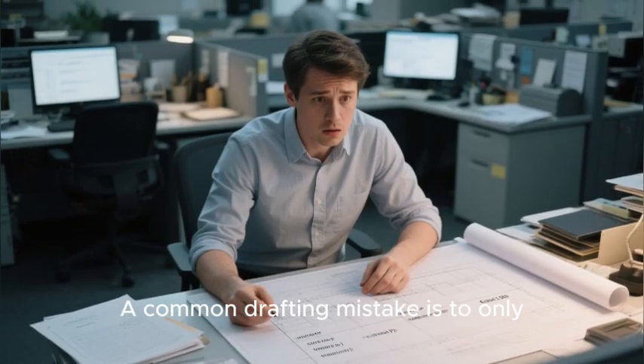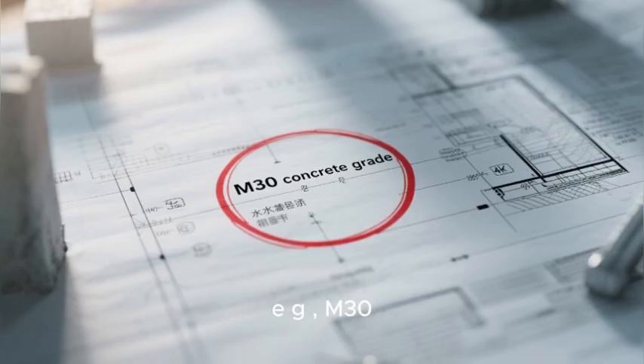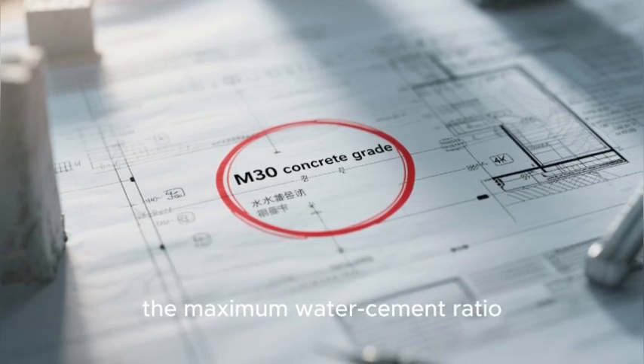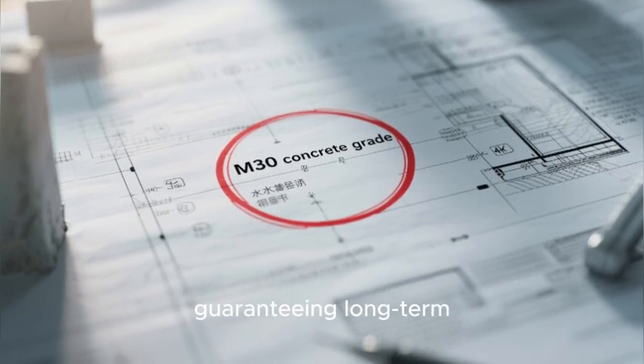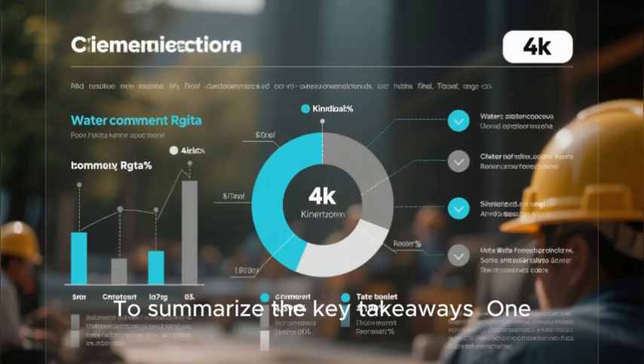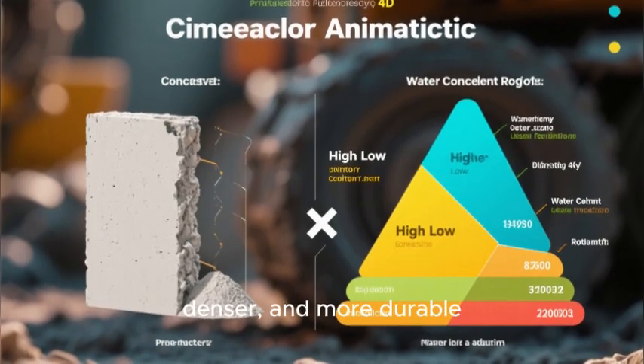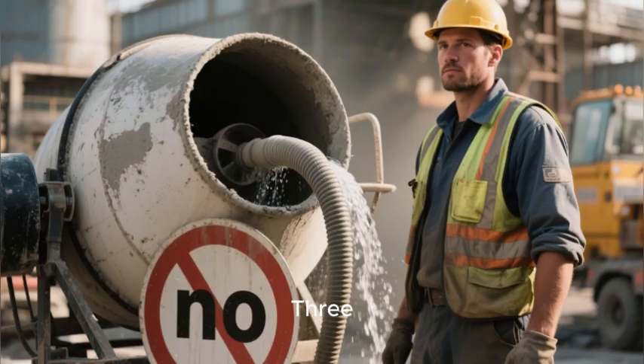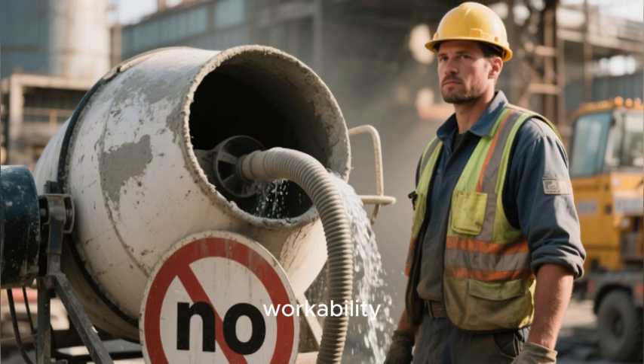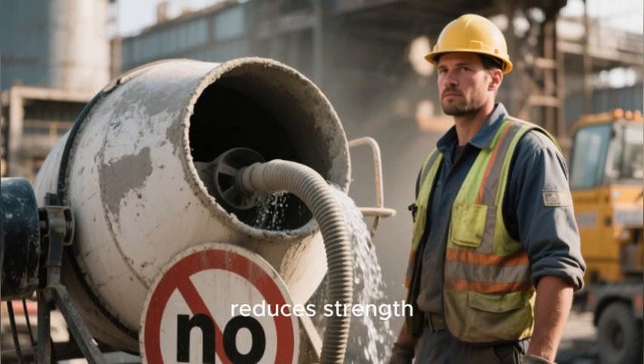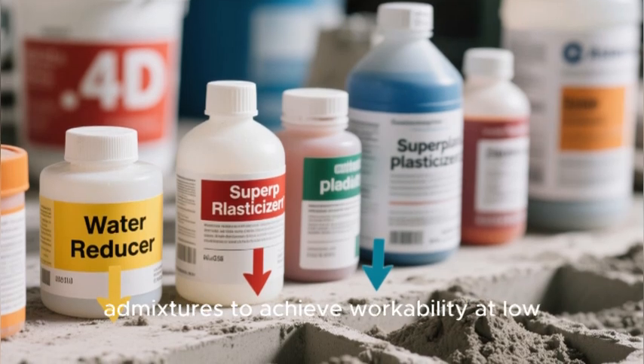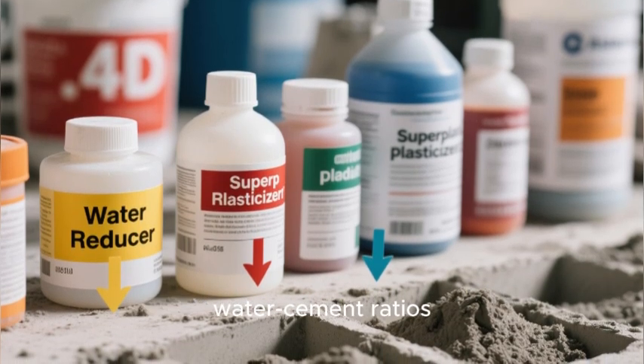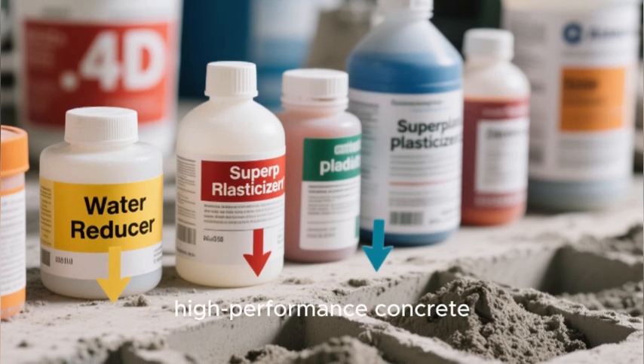A common drafting mistake is to only specify the concrete grade, e.g. M30, without also specifying the maximum water-cement ratio, which is essential for guaranteeing long-term durability. To summarize the key takeaways: 1. The water-cement ratio is the mass of water divided by the mass of cement in the mix. 2. A lower ratio means stronger, denser, and more durable concrete because it leaves fewer water-filled pores after hydration. 3. Never add water on site to improve workability. It permanently and severely reduces strength. And 4. Use water-reducing admixtures to achieve workability at low water-cement ratios, which is the hallmark of modern, high-performance concrete.